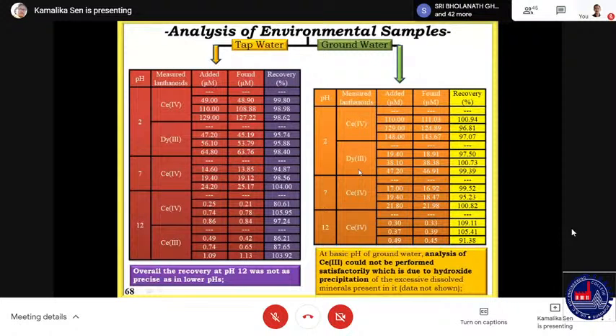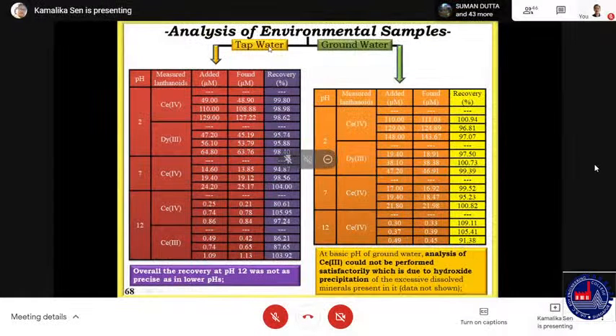So we tried to have a practical application of this kind of sensing, and we studied with some tap water near our Rajabazar campus and groundwater near the Sundarban area, and we have studied to find the recovery percent of these elements from the natural water that have been collected, and we can see that the experiment also behaves perfectly in presence of the natural water collected from the locality.